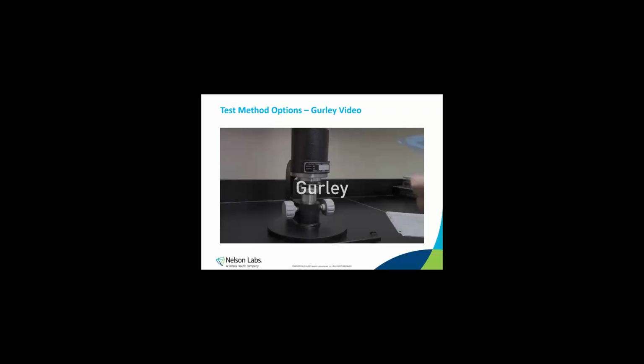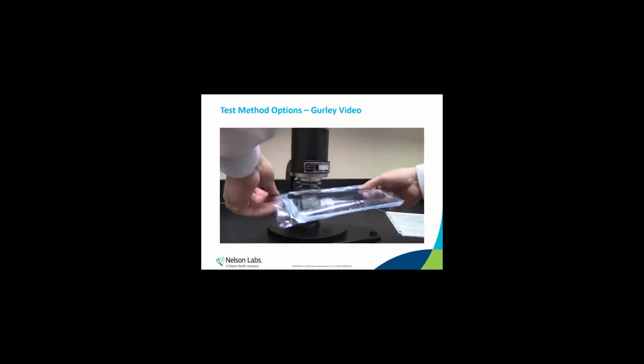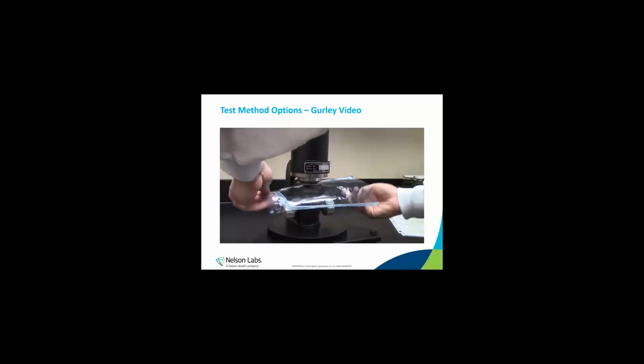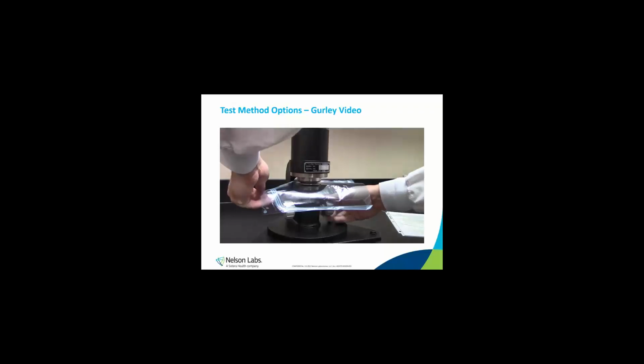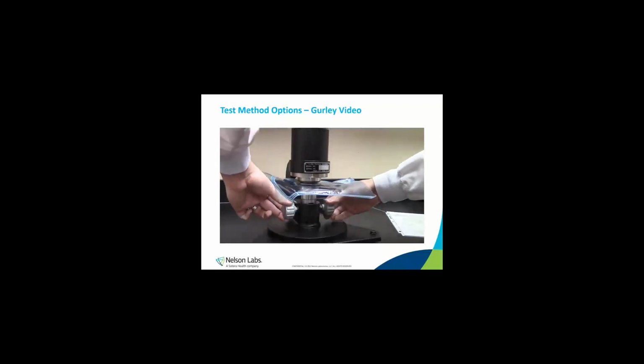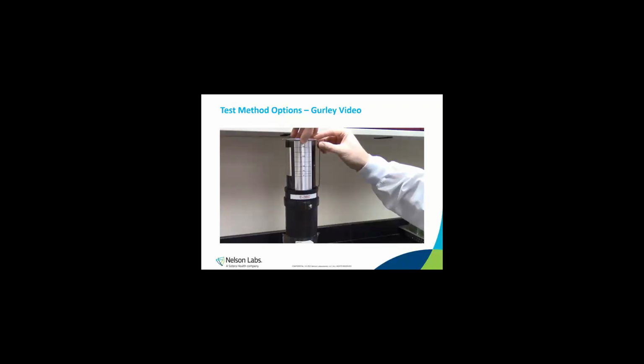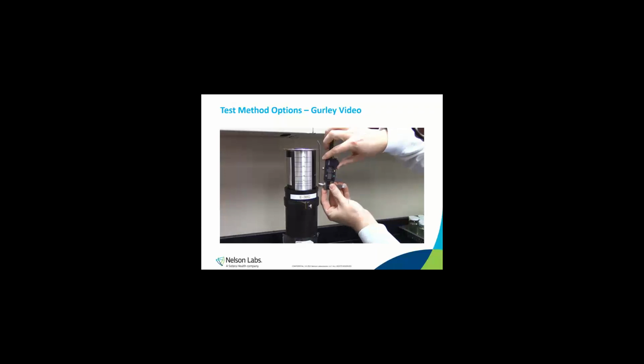Now let's look at the Gurley. This is a very simple and straightforward test, and it's for non-porous materials. We're going to take this material, we're going to put it in the tester and clamp it. And then we're going to release this cylinder and measure the distance. Now, if this were a porous material, that cylinder would continue to drop until it reached the bottom.